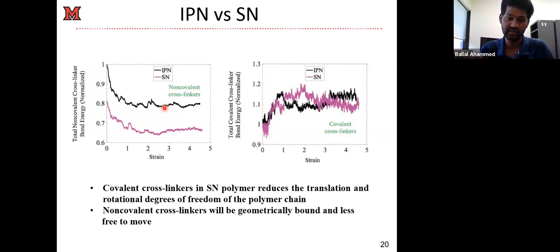It kind of fixes and reduces the other degrees of freedom, which actually discourages the non-covalent bonds from forming with the other polymer chains, because they need to come in contact within a certain radius with the other non-covalent crosslinkers. But if the covalent crosslinker reduces their degrees of freedom, it creates an unfavorable situation for the non-covalent crosslinker to crosslink with the other non-covalent crosslinker. That's why the number of non-covalent bonds is decreasing in the SN network.